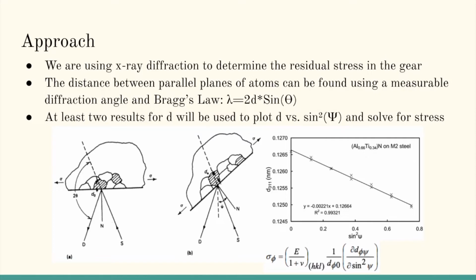Two measurements are taken at different angles of psi, which is the angle between the surface normal and the angle bisector of the incident and diffracted beam seen in figure B. These values for distance are plotted on a graph versus sine squared psi, similar to the graph shown. Stress is solved using this equation, where the slope of this line is input here.